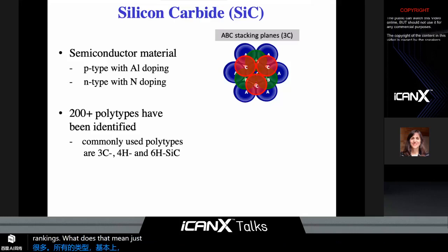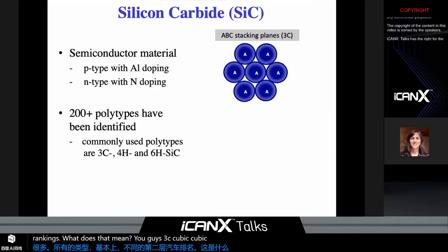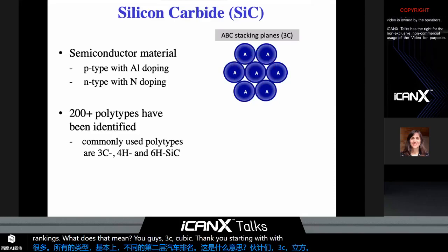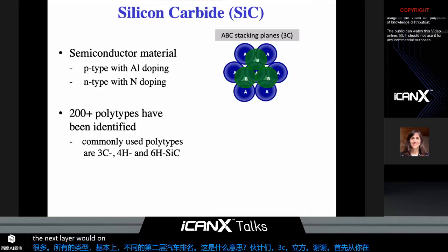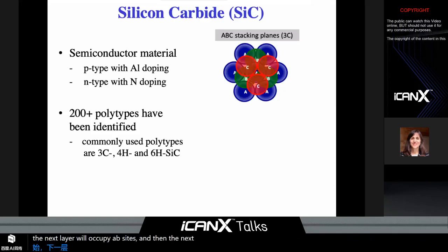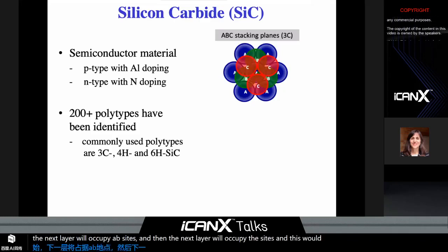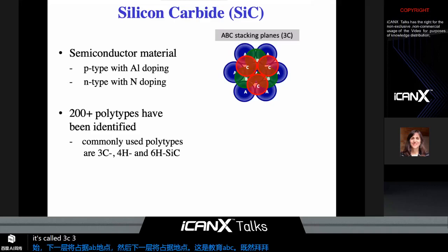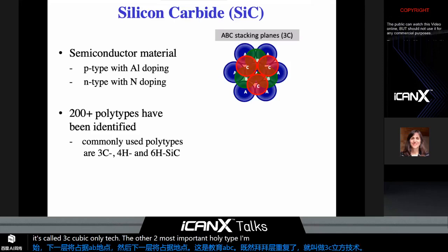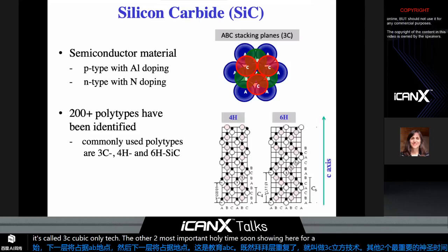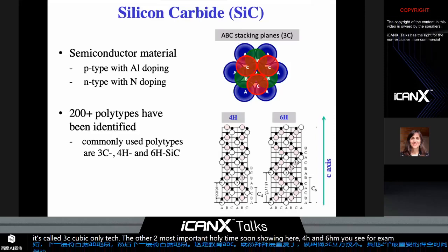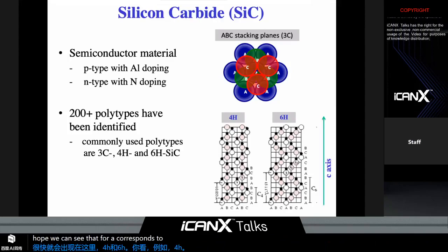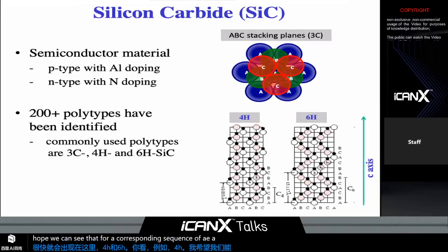Let's look at 3C cubic stacking, starting with the bilayer A, as you see here in blue. The next layer would occupy the B sites, and then the next layer would occupy the C sites. And this would repeat ABC, ABC. Since there are 3 bilayers that repeat, it is called 3C cubic polytype. The other 2 most important polytypes are shown here, 4H and 6H. For example, 4H corresponds to the stacking sequence of A, B, C, B, A, B, C, B.